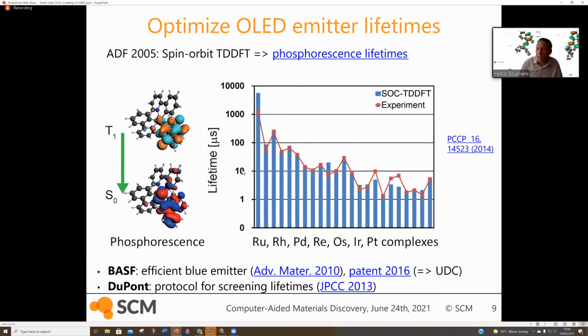Obviously, lifetime is important, but also the color. And so what's particularly important for very sharp OLED screens is that you have narrow emissions. And so here's an example for a platinum complex where actually the emission is not so narrow, it's rather broad. But you can calculate this vibrational broadening by using Franck-Condon factor calculations. And as you can see, in red, this is the calculated spectrum. And here is the measured spectrum at room temperature. So we use, of course, just simple Lorentzian broadening or Gaussian broadening. But you can see there's pretty good agreement in the color shape between the calculated and the measured spectra. So again, you can use that as a quick tool to screen the emission profile of your OLED emitter.